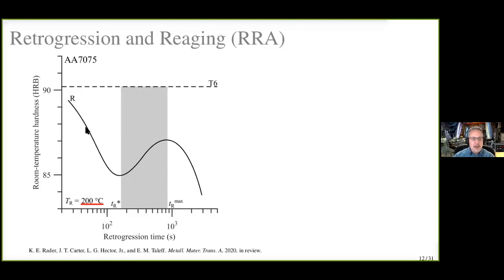And the hardness drops down with increased time at temperature until we get a minimum here. And that minimum right here is a time we call TR star. We can measure where the minimum is, so it's a critical time for us to measure experimentally. But then the hardness goes back up here, and we get a maximum, and we call that retrogression time max. And then the hardness continues to go down. Now, if we take this material that's been retrogressed for a certain amount of time and we apply a reaging heat treatment, we can then recover that strength or hardness that was lost.